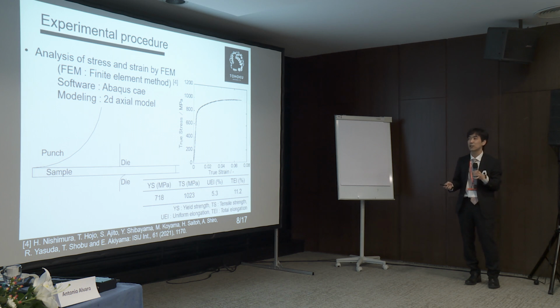FEM was processed by Abaqus CAE using 2D axial models to obtain the distribution of stress and strain. We actually use this model, and this is a stress-strain curve of the material obtained by tensile test.